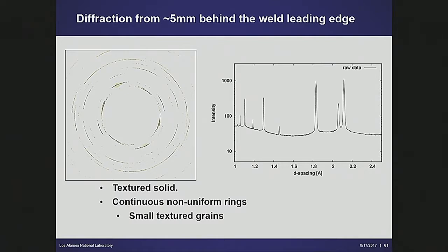About 5 millimeters behind the weld pool, right? The material is now uniformly solid, but it's cooling down, right? If you look, the rings are pretty continuous here, right? There's lots of spots in them, but they've got big breaks in them. That's sort of consistent with the material being textured.